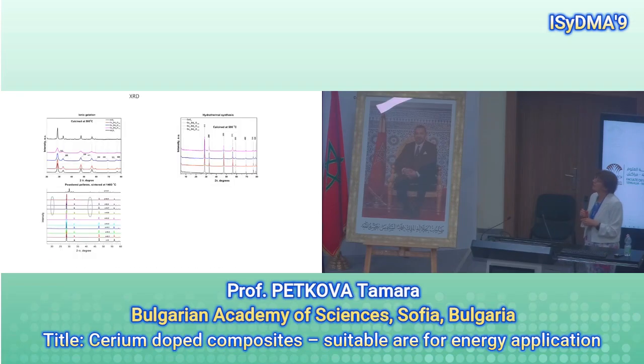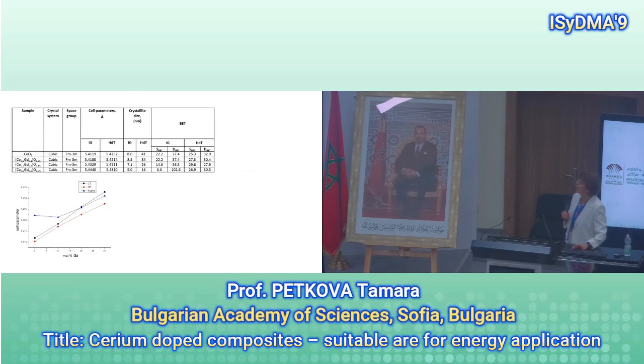We started with characterization of the obtained samples. The sample obtained by ionic gelation at 500 degrees centigrade shows peaks that are broad. Due to the presence of gadolinium, which has an ion radius higher than that of cerium, after the calcination the peaks become sharper, and likewise for the hydrothermal synthesis, which is evidence of the high crystallinity we obtain in these samples.